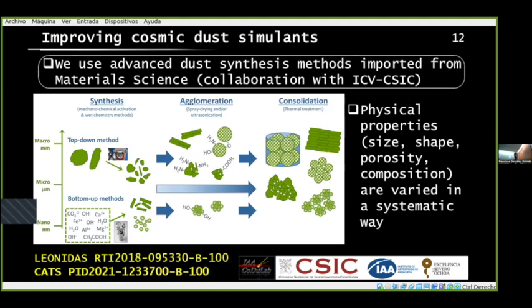And then when we have our samples, we are able to measure the scattering matrix by varying the properties of the particles. These are different methods. This is the so-called top-down method. Basically, what you do is grind down, mill, pieces of minerals to micron sizes. Or you can also use a bottom-up method, which is basically a gas-to-particle conversion method where you generate particles by mixing chemicals, both ionic or neutral, with very high dipole moments. And then once you have the particles in the micron size or the nanometric size range, you can start agglomerating them using different techniques, and then you get micron-size agglomerates. And then you can go a step further, and using consolidation techniques, you can get millimeter-size aggregates, which are the ones that we assume are present in 67P and were not detected before.